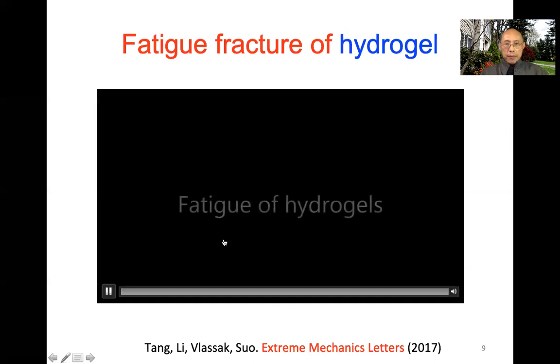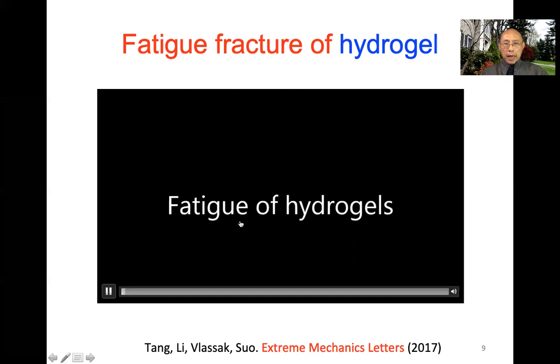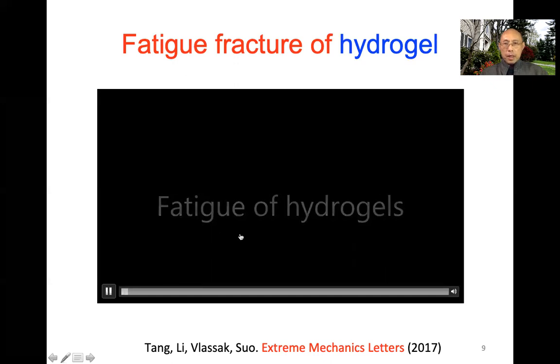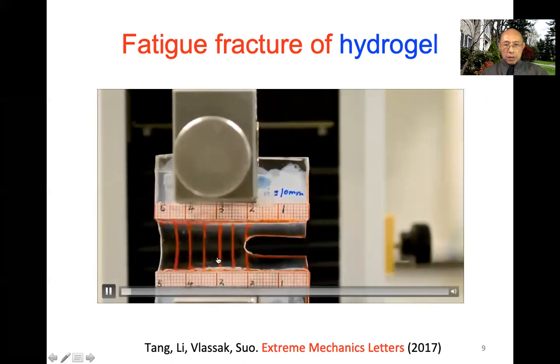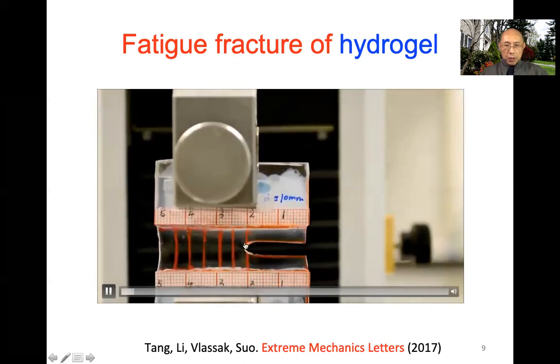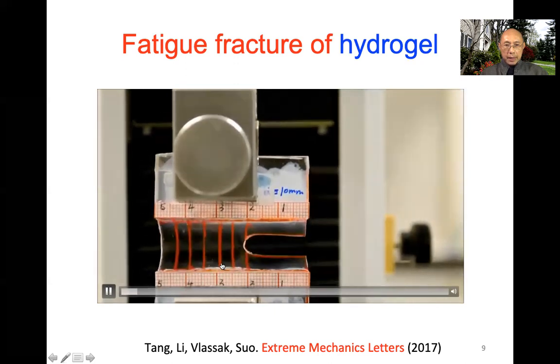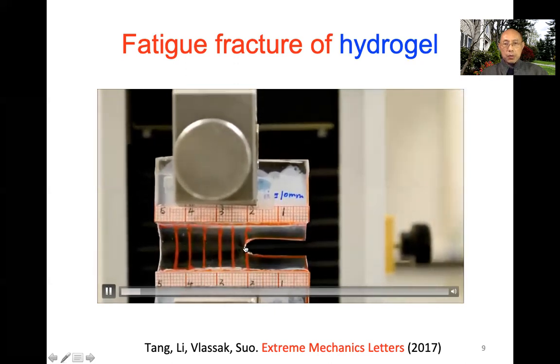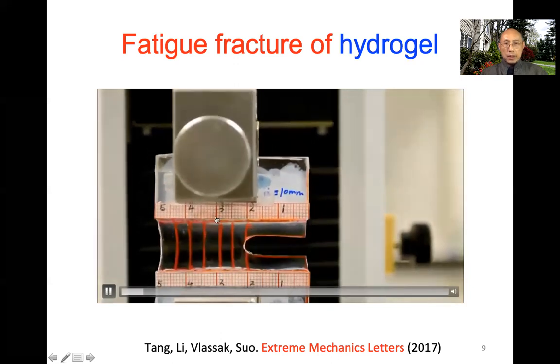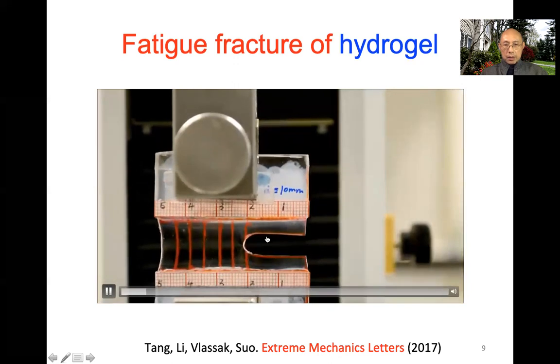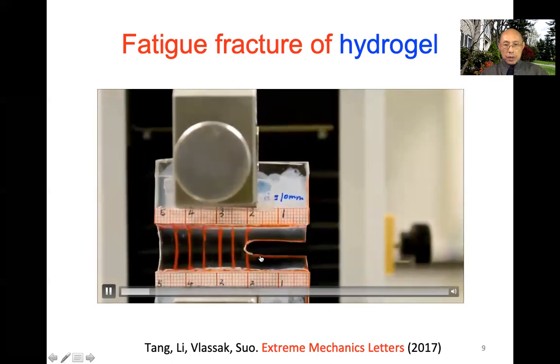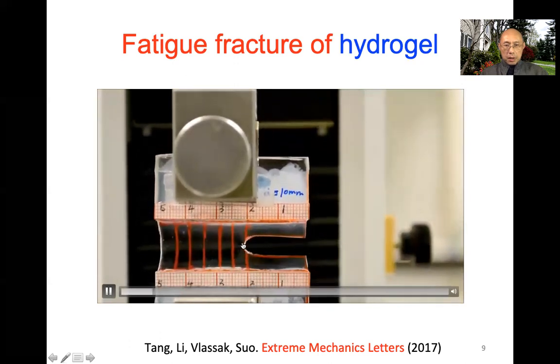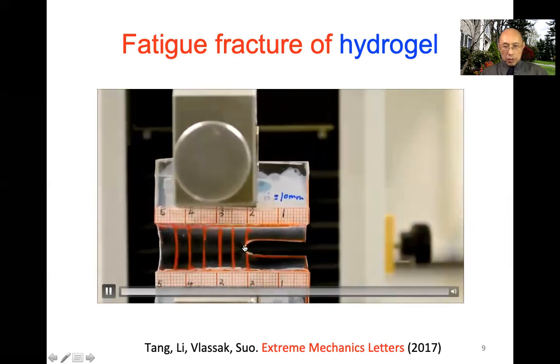Let me just jump directly to a picture, an experimental picture. So this is a video. This is how it looks. We have polyacrylamide. This is a polyacrylamide gel, transparent. On the surface of the gel, we mark with a red dye, so we can see the location of the crack. We apply cyclic load, up and down. The crack opens and closes.